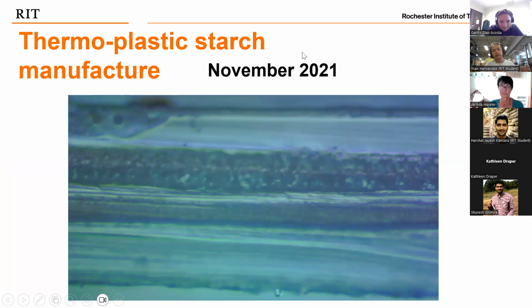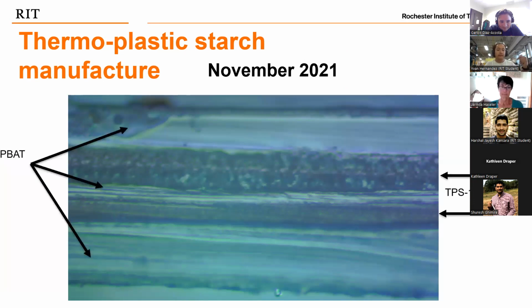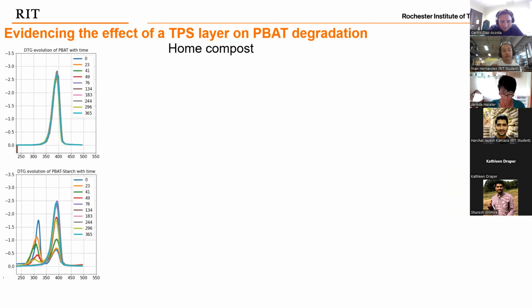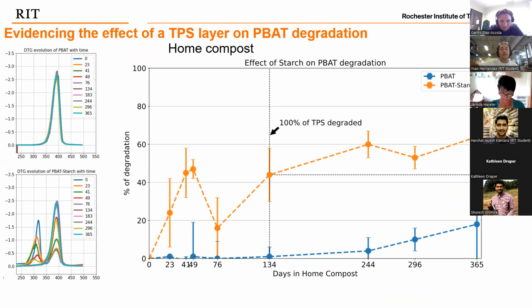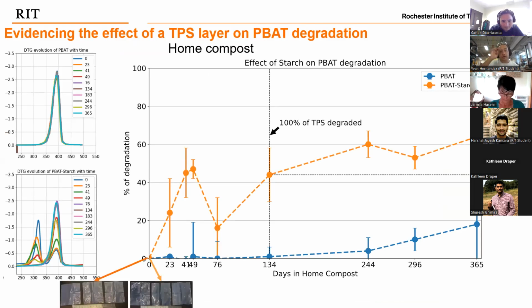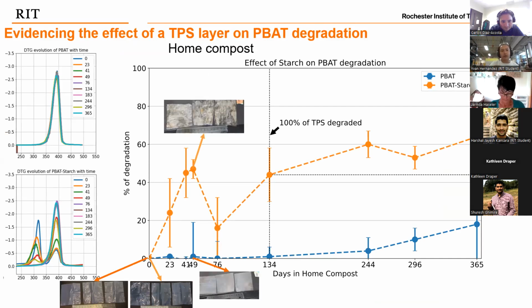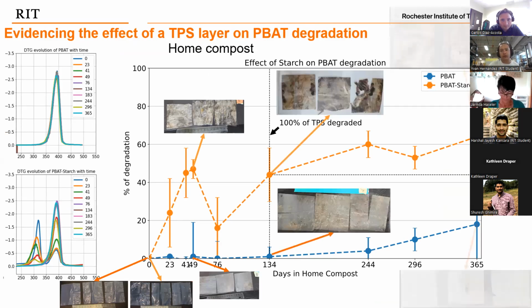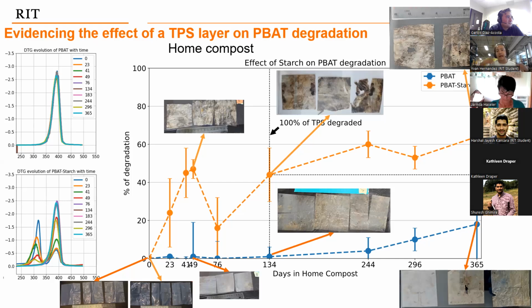So from there, we were able also to get some samples to understand what is the effect of that thermoplastic starch on the PBAT degradation, and trying to evidence that it is actually going to degrade faster. So in a home compost environment, we analyzed how the loss of starch, the degradation of starch, was going to increase the PBAT degradation. And so here with some pictures, you can see that not only the weight of the starch film is gonna be lost faster, but also it's gonna fragment more. And that is very important for degradation because it gives higher surface area, so more space for the microbes to eat.